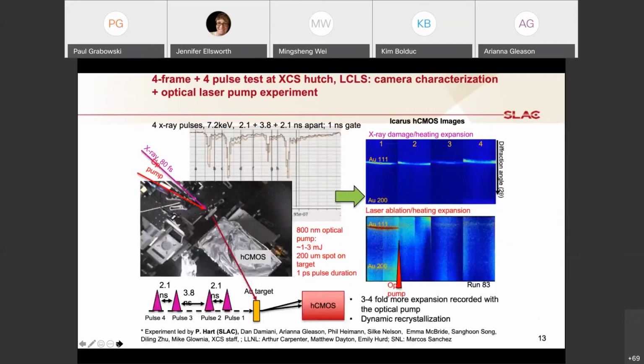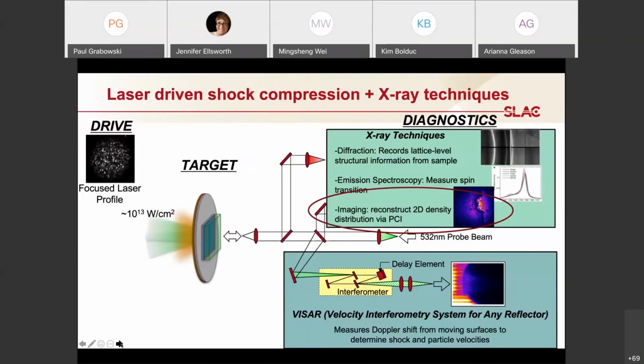We've also tried to combine this with a separate pump, a very small optical laser, only a few millijoules, unfortunately. But we executed a similar setup, this time pumping a gold foil with this small laser, and we had a different suite of X-ray pulses, this time 4 in a row, probing the gold. So these operational parameters are available to you, and I'm going to show how we've also deployed them with the long pulse laser. So the heart of the talk here is focusing on this third diagnostic.